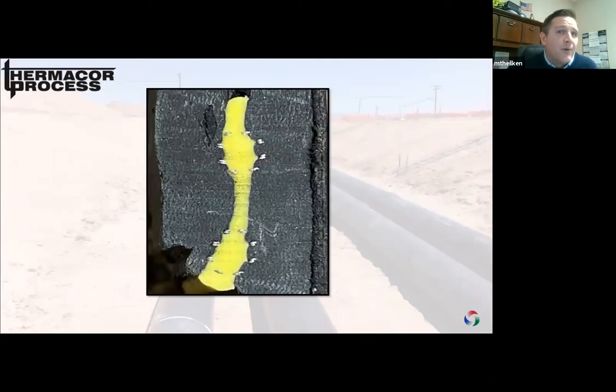So in this next picture, we're demonstrating a cross section of the fusion weld. In performing the tensile strength test on this joint, the material actually fails on the jacket as opposed to the weld, as the weld becomes stronger than the material surrounding it. So you can visually see that there's absolutely zero pathway for water ingress into a system that's sealed with this closure. And so really it's the best way to guarantee a proper installation. We're always going to require a log sheet to be completed with the pressure test information on each joint in order to issue that warranty, so that we can confirm that it's done correctly.